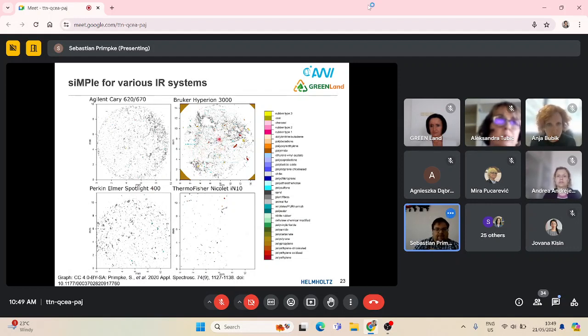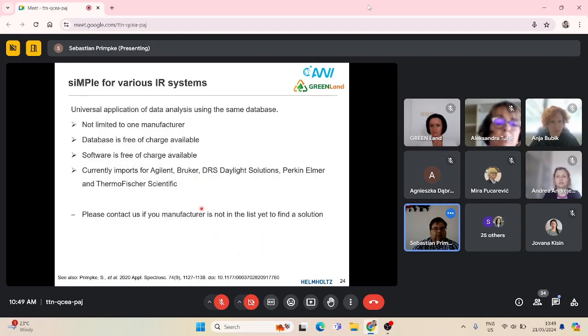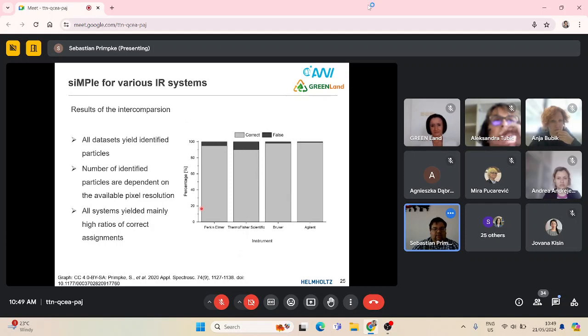And you see here it worked quite well. We found microplastics in every sample and could also identify them quite well. So we're not limited to a manufacturer. For example, if you have another system, like the one from Shimadzu, just contact us. We'll try to figure out a solution and how to implement your data into our software. Using this software, we were really surprised that it identified all particles in every sample, and with a really high success rate. We only had low error values, but still we ended up with around 5% misidentified, but this is the limit we have set for the accuracy of our automated data analysis.